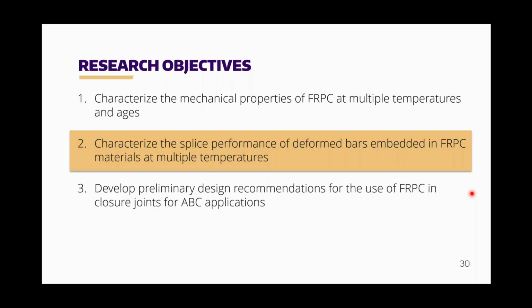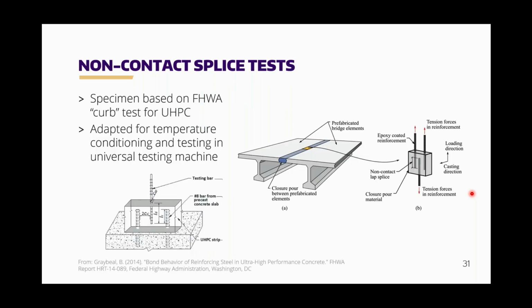So the next phase of research was to look at the splice performance. We utilized the results from the mechanical properties testing to create a good bracketing for all of our variables, as well as giving us a little bit of heads up as to some of the results that we could see. We utilized non-contact splice tests. This is similar to curb testing, which was done on UHPC at the FHWA. The specimen that they used is shown in the lower left-hand corner on your screen. We adapted that a bit, both in how it was tested and what the specimens looked like, to be able to test at different temperatures as well as to fit the testing in the lab that we had at the University of Washington.